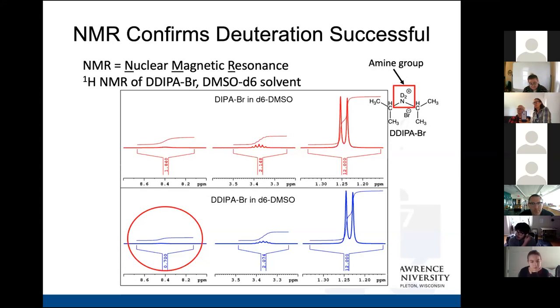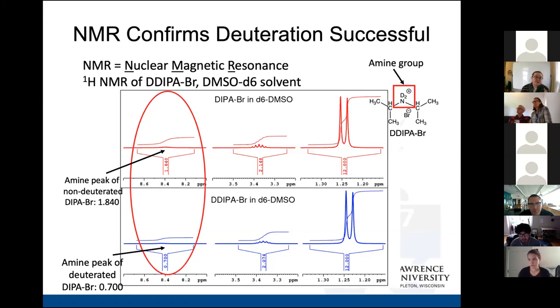Remember, it is the amines that we want deuterated since the amines are part of the compound involved in the hydrogen bonding, which could be a key to understanding the mechanism of ferroelectricity. Since the compound is deuterated, we would expect the amine peak to be significantly decreased in comparison to the non-deuterated DIPA-Br spectra, since there would be deuteriums instead of hydrogens on the amines, and deuteriums don't give off a signal in proton NMR. And lo and behold, when compared to, yes?